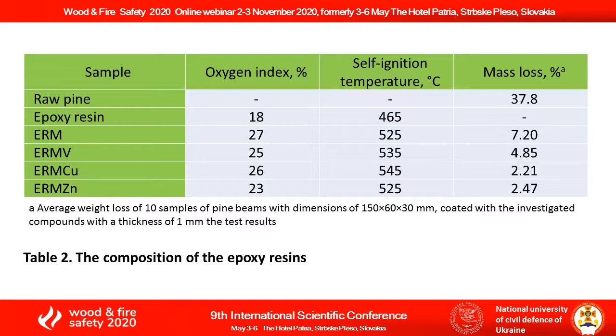As can be seen from Table 2, the modification of the epoxy polymer with activated basalt scales and monoammonium phosphate, composition ERM, transforms the ER coating from the class of combustible material into self-extinguishing, OI 27%. Self-ignition temperature of this composition is 525 degrees Celsius. Testing of wood samples treated with the tested compound shows that this coating provides first group of fire retardant efficiency with an average weight loss of 7.20%.